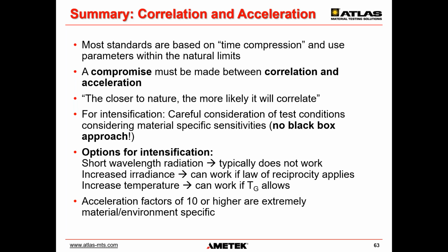Options for intensification: short wavelength radiation typically does not work. Increased irradiance can work if the law of reciprocity applies, and increased temperature can work if the glass transition temperature allows. So you should always be above or below it. You should not cross it, or you should not have a different state in the test than you have outdoors. I hope you got that message in these slides. Acceleration factors of 10 or higher are extremely material and environment specific. Be careful. Be very careful.